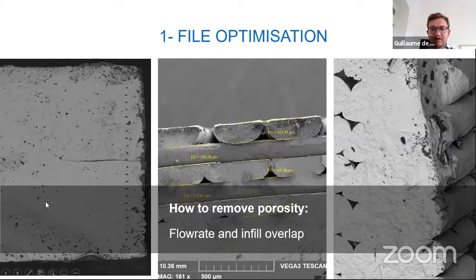This kind of defect, which is just on the outside, is a bit different. It's actually because there's a bad junction between the shell and the infill. And again, there's one parameter for that, called infill overlap, which will tell you how much the infill is going to overlap on the shell. It needs to overlap a bit, typically 30 to 50%, to avoid that kind of defects.